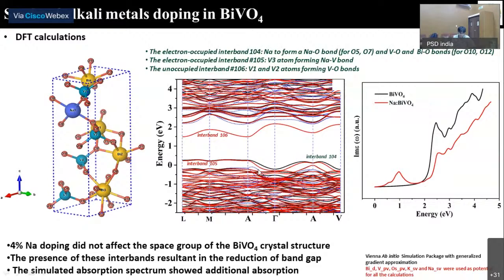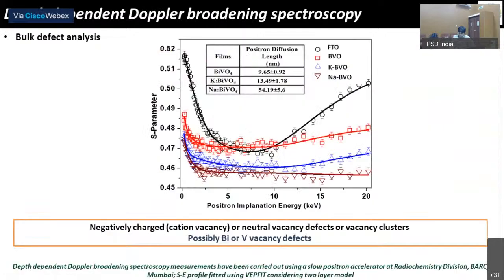Then further we have analyzed the bulk defects using depth dependent Doppler broadening spectroscopy. So in this, basically the S parameter is analyzed with respect to the positron implantation energy, and the positron diffusion length for different samples is calculated. So we can clearly see for bismuth vanadate, the positron diffusion length is around 9.6 nanometer, whereas it is most for sodium doped bismuth vanadate, that is around 54 nanometer.